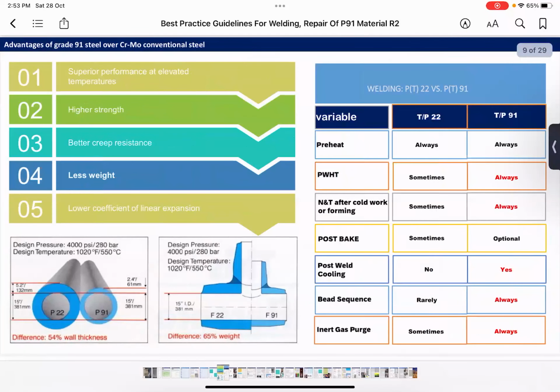So the advantages or the differences between P91 as compared to P22. It has superior performance at elevated temperature, higher strength, better creep resistance, lesser weight, and lower coefficient of thermal expansion. And in the photos below, we see the difference in weight and the difference in wall thickness. So you can save up to 65% of the weight when using P91 material. And the difference in wall thickness is around 50%.